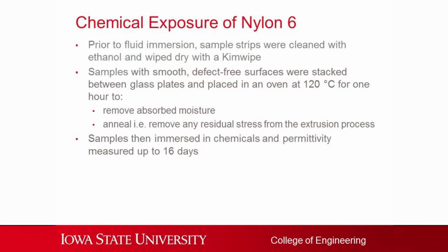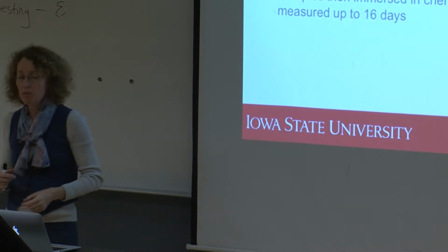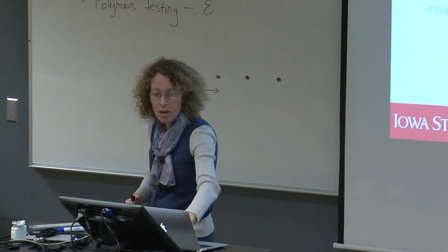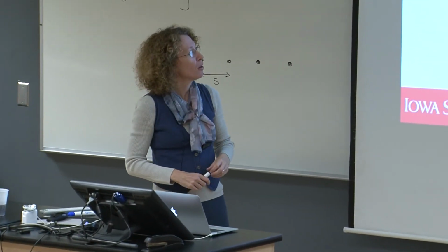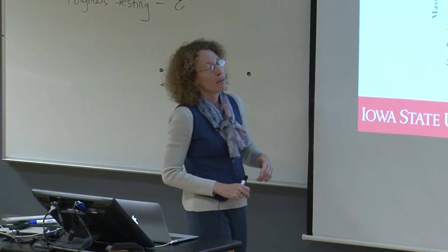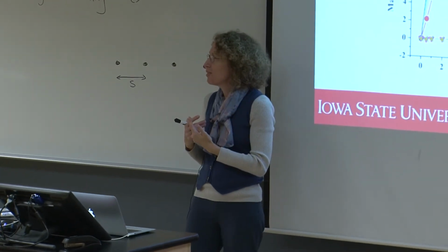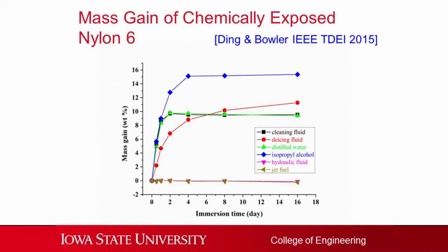Okay, so we prepared a few samples. They're basically smooth, clean sheets. We actually heated them in advance to remove any moisture that might be present before we started. And then we immersed them in these fluids for a couple weeks. Okay, so here's a nice simple measurement that you can do without a lot of equipment. How does the mass change when you've immersed these samples in these different fluids? So let's have a look at that.